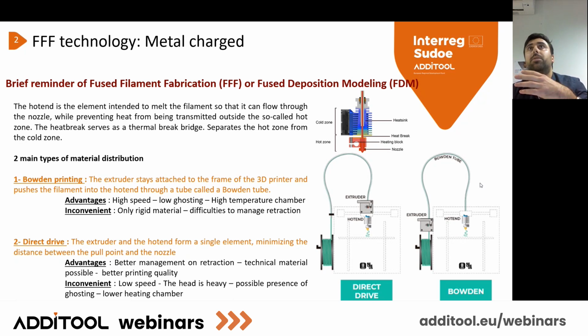The ghosting is the vibration aspect we can have on a part when we are printing an edge, for example. When the part goes through the 90 degrees edge, we have a vibration, and we can see it directly on the skin of the part. So with this kind of Bowden printing, we have low ghosting, and also, because we don't have any electronic card or PCB, etc., we can have a higher temperature of the chamber, so we can increase more than 80 degrees, 100 degrees on the temperature chamber.